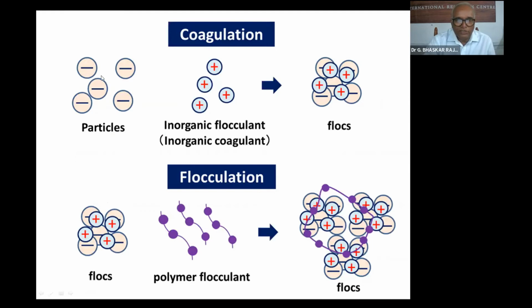Now, for example, these are the particles, all negatively charged. You introduce some positively charged salt, and when it goes positive, the charge gets neutralized and it forms a flock like this. As I mentioned earlier, either alum or ferric alum can be used to achieve these flocks. If you want to make bigger flocks, you use polymeric flocculants, which make a bigger flock that can settle down very easily. So flocculation is mainly achieved by adsorbing polymer molecules.